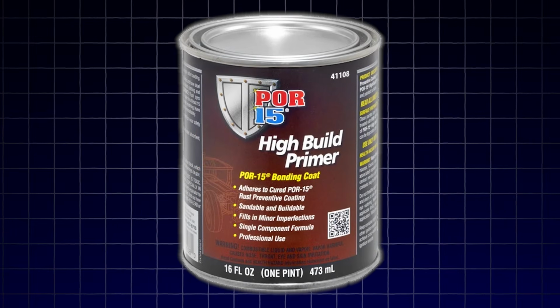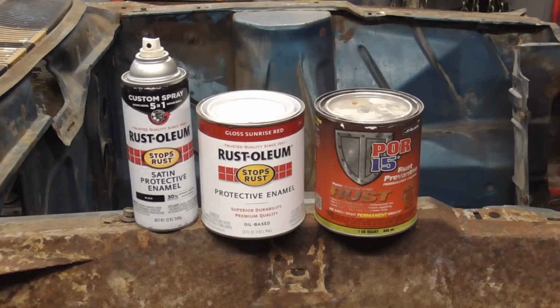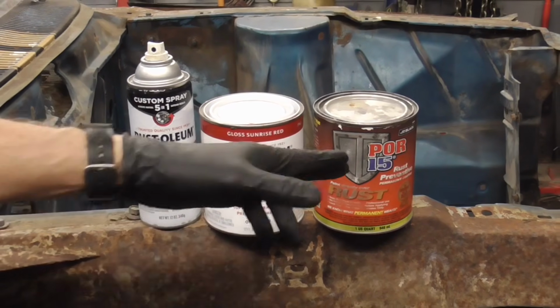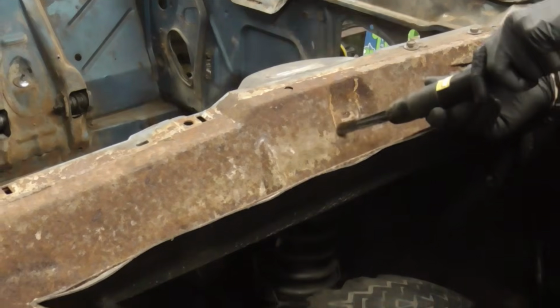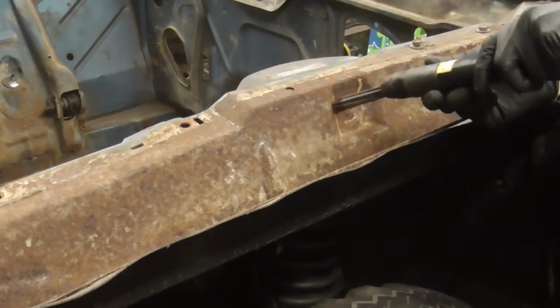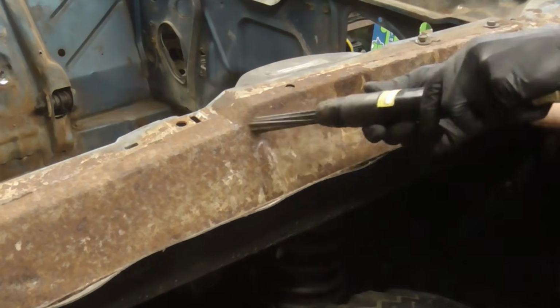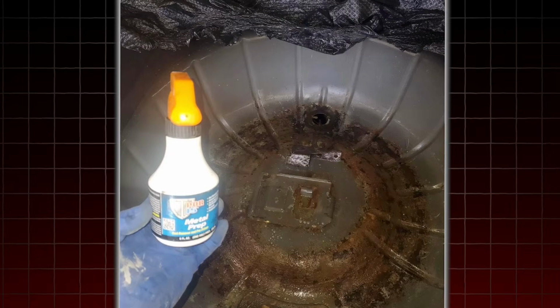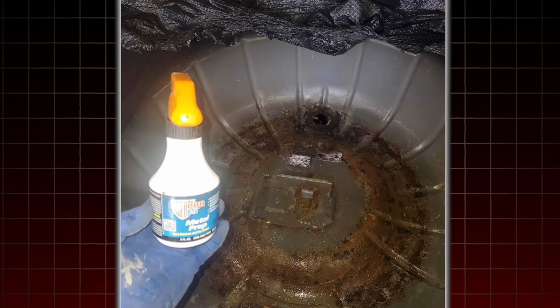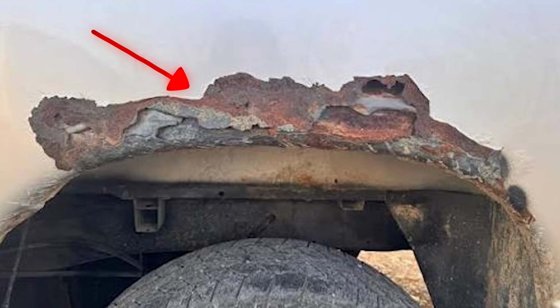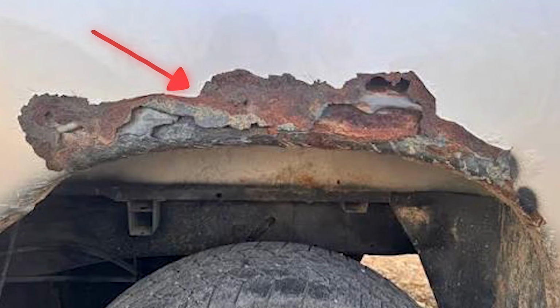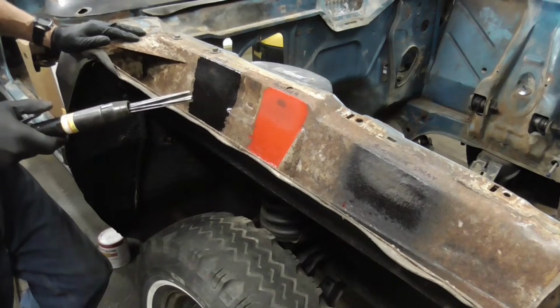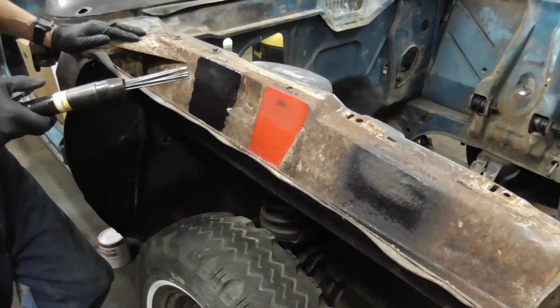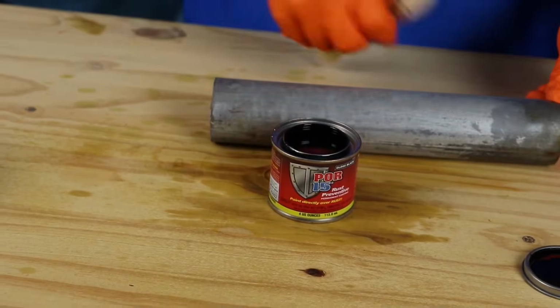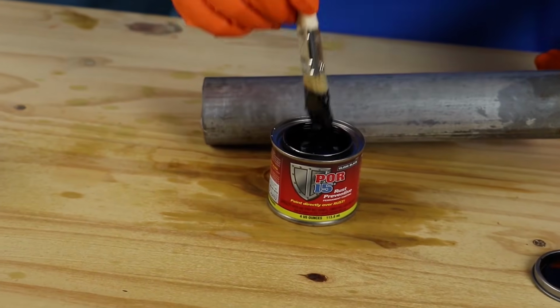The limitation is film build. The tie coat primer is formulated for thin film application as a preparation layer. On pitted frame rust, thin film application allows the primer to bridge over pit openings, rather than penetrating into the pits where the most active rust is progressing. Bridged pit openings trap moisture inside the pit cavity beneath the primer film. The same moisture trapping problem that affects inadequate chelation treatments affects thin film primer products applied over pitted rust.